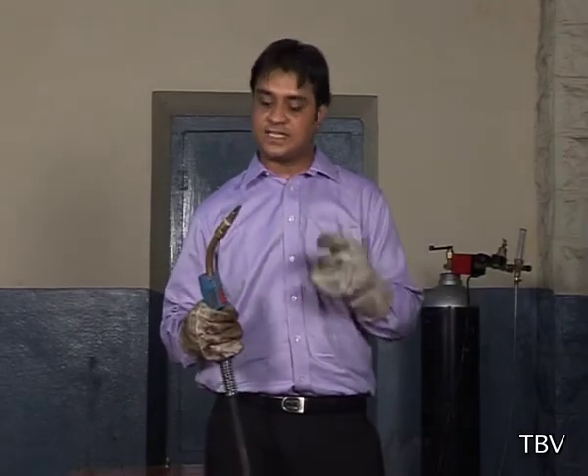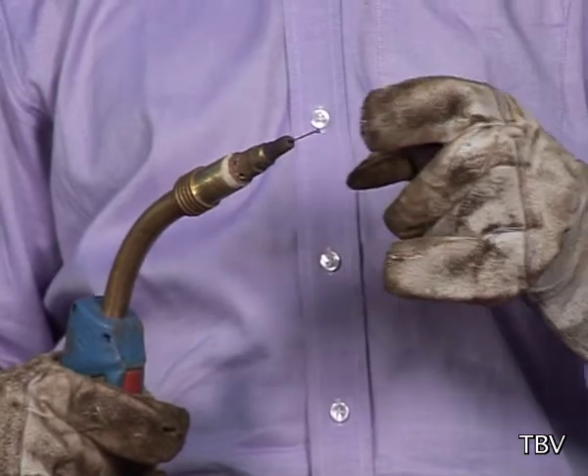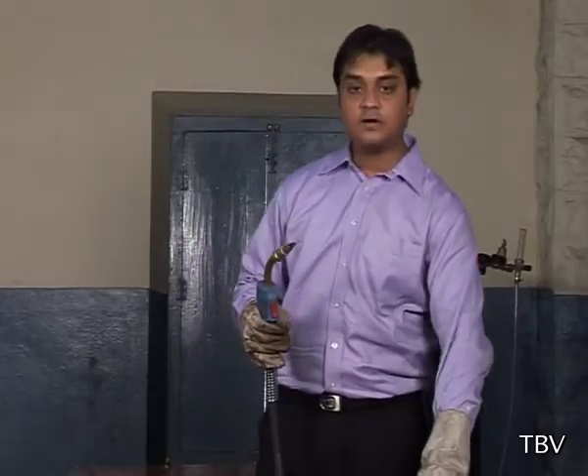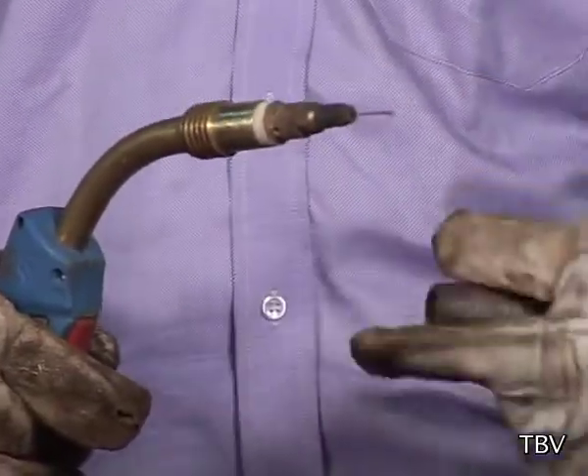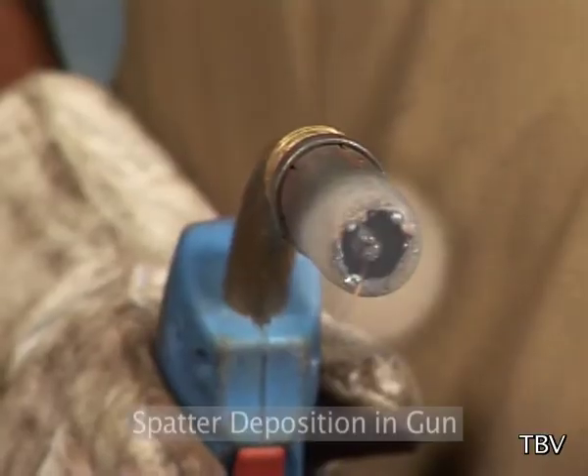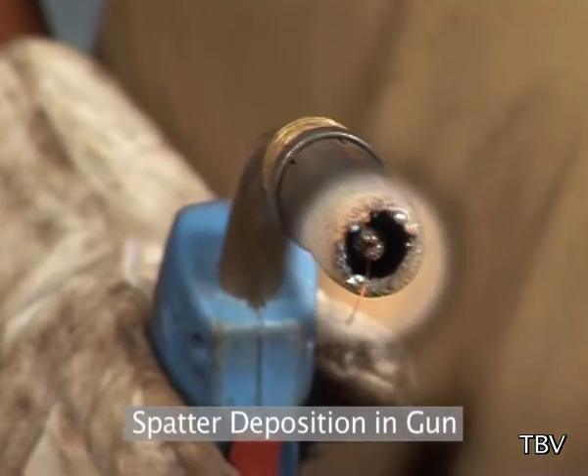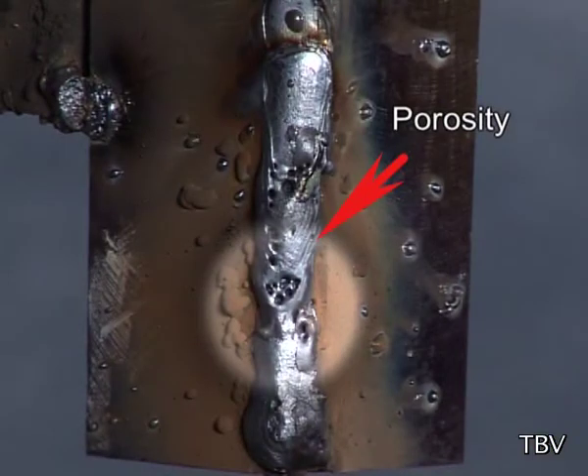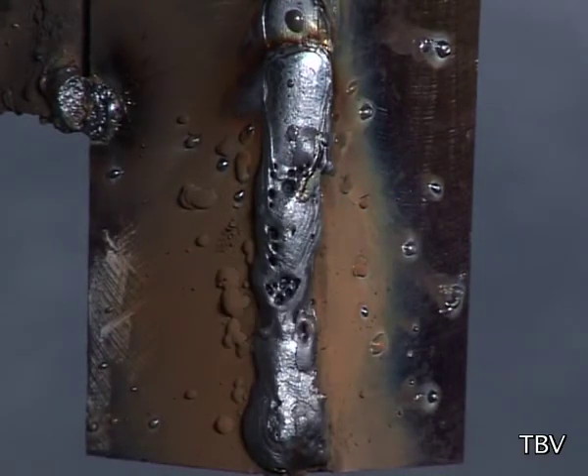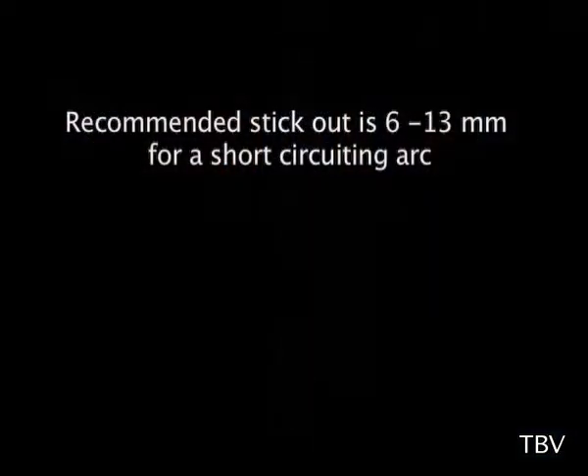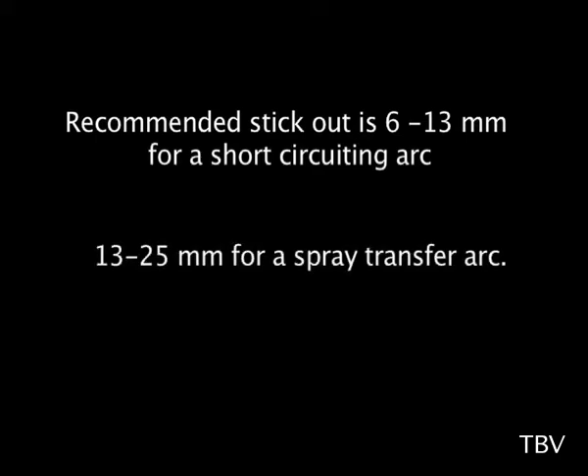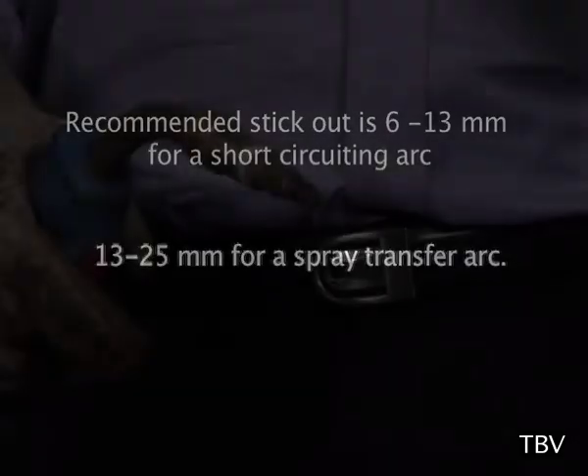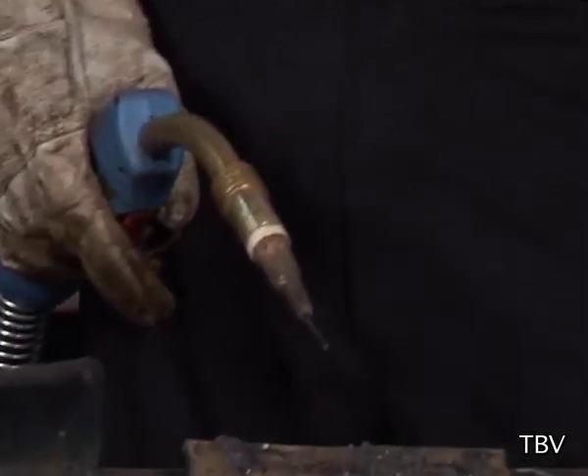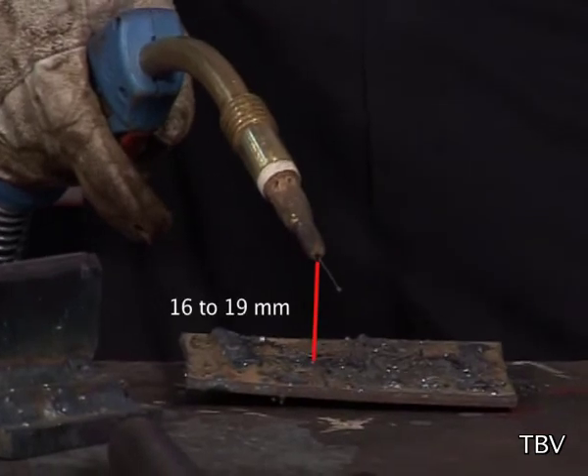Stick out. This is a welding gun. Stick out is the distance between the tip of the nozzle and the tip of the electrode. Now, if the stick out is too short, excessive spatter will deposit itself onto the nozzle, restrict the shielding gas, and in turn cause porosity in the weld. Recommended stick out is 6 to 13 millimeters for a short circuiting arc and 13 to 25 millimeters for a spray transfer arc. Of course, generally the distance between the work and the nozzle should be 16 to 19 millimeters.